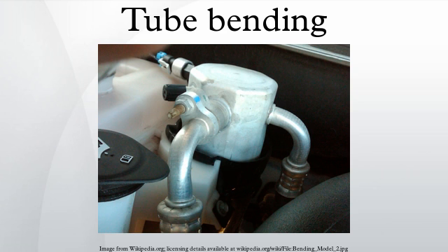Bending springs. These are strong but flexible springs inserted into a pipe to support the pipe walls during manual bending. They have diameters only slightly less than the internal diameter of the pipe to be bent. They are only suitable for bending 15 and 22 mm soft copper pipe or PVC pipe. The spring is pushed into the pipe until its center is roughly where the bend is to be. A length of flexible wire can be attached to the end of the spring to facilitate its removal.